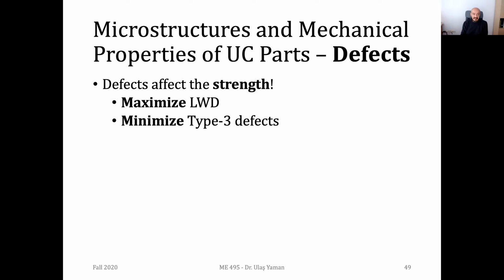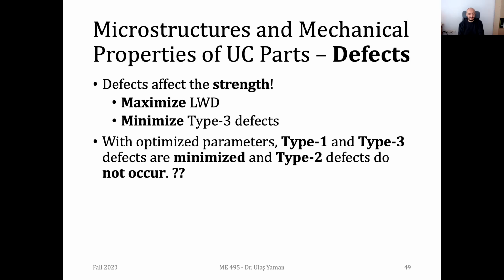So how are we going to eliminate these defects? Since these defects are obviously affecting the strength of our product, we need to remove them by doing some modifications on the parameters, or maybe using some specific equipment. So to increase the strength, we need to first increase the linear welding density. The interface between the layers should be proper. And another thing we can do is to minimize the type 3 defects, which were the defects on the top surfaces on the same layer. If you have gaps between adjacent foils, then it's called type 3, and we can simply eliminate it by properly depositing these foils on the layers.